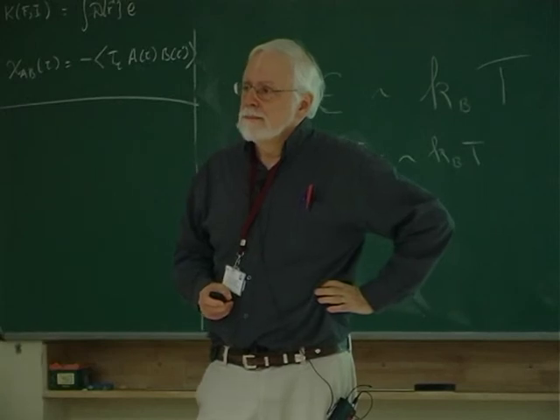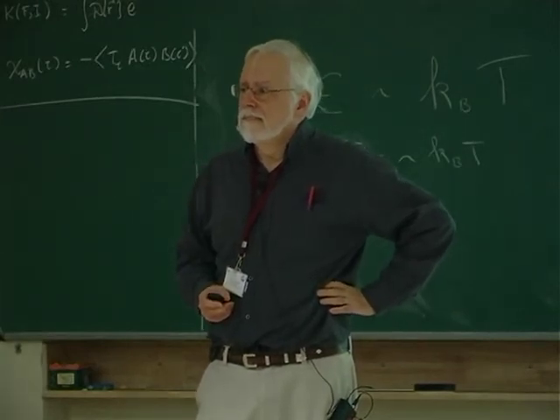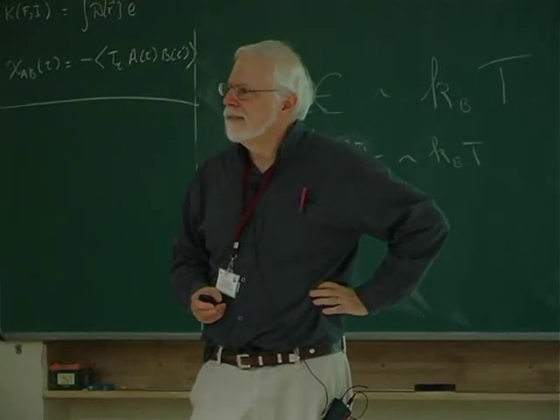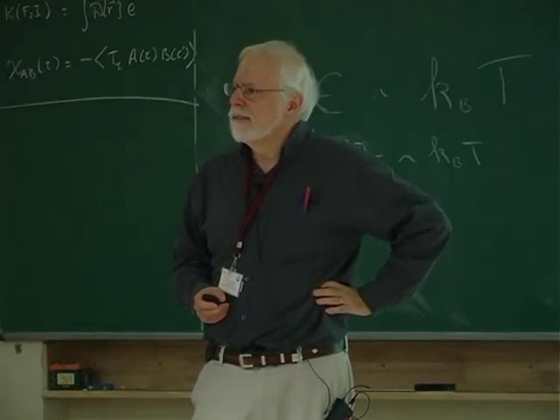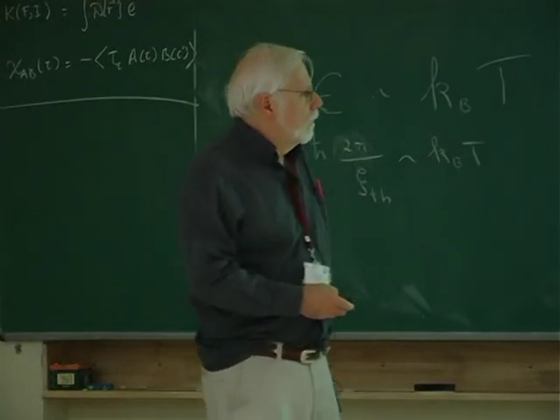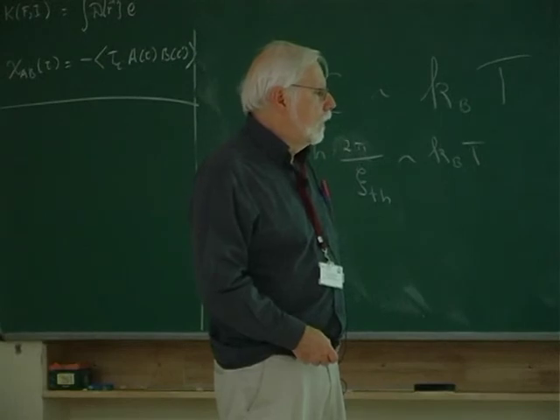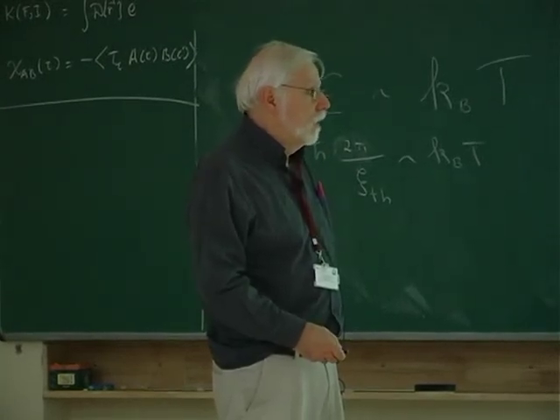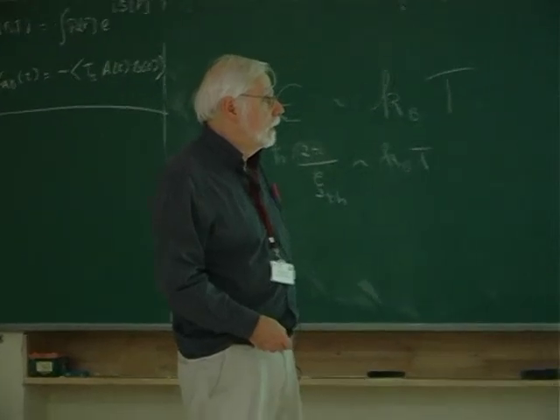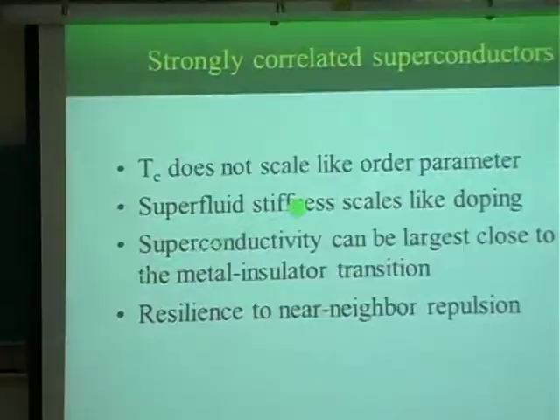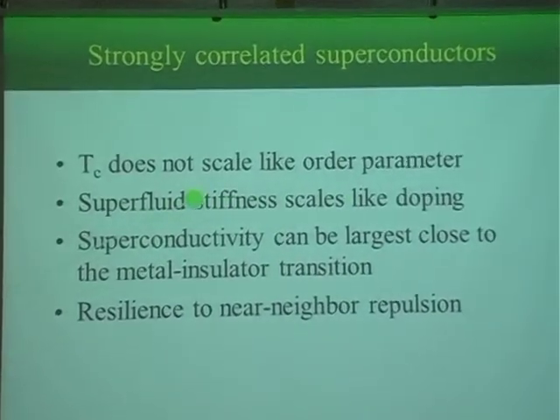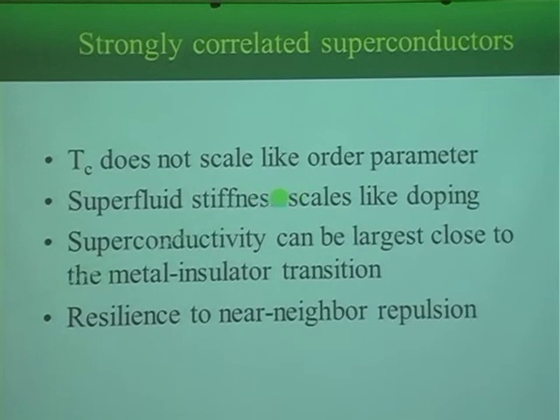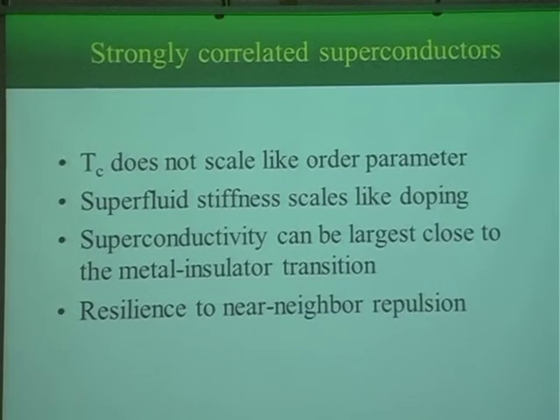Yes. Another question: for strong coupling superconductors, does the disorder have any other effect other than this pseudogap? Any special effect? Disorder plus strong correlation? Yes, there is a very strong resilience to nearest neighbor repulsion that is not found in the weak coupling case. And this TC does not scale like the order parameter. I don't have any theory behind this now, but this is more like speculation. Actually, it's an experimental observation, which I like to attribute theoretically to the strongly correlated case.